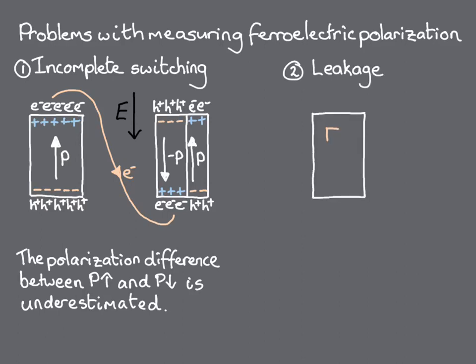In our second example, our ferroelectric material is leaky, in the sense that it is not robustly insulating, but contains free or weakly bound electrons or holes coming from point defects such as oxygen vacancies or donor atoms.